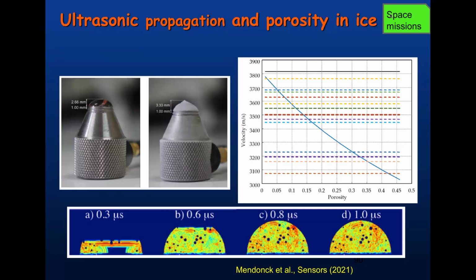We also simulated the drop. We introduced some porosity on the drop, and you can see the transmission of the pulse and also the reflections. Like here, you see it. The ultrasound reaches the surface of the drop, and then it goes back. When there is little porosity, you see a much better reflection. When you increase the porosity, you lose a lot of ultrasonic signal. But the important thing is that you can relate this to a porosity level.